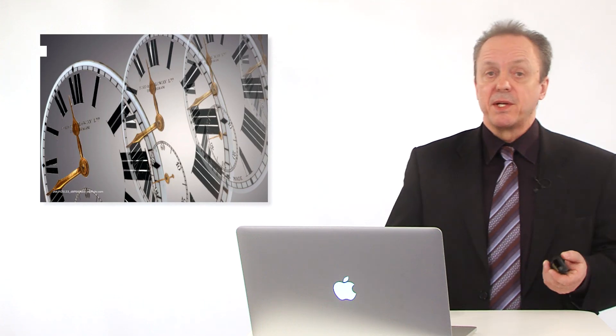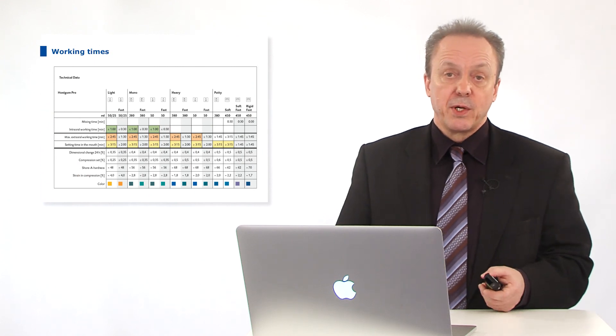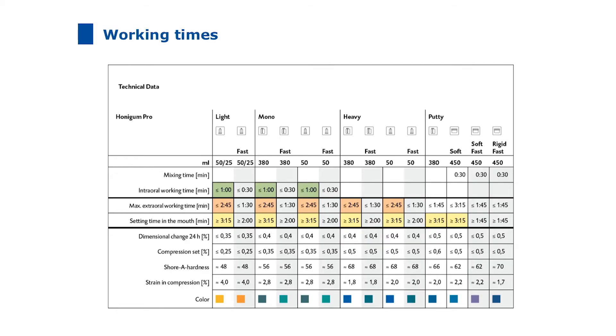You know the many different materials with many different setting and working times. Even if you want to go faster, Honigum Pro has the ideal impression material for you. For all Honigum Pro mixture materials, we now have the same intraoral setting time of 3 minutes and 15 seconds. And when it has to go faster, all variations are available in a fast version as well — the setting time in-mouth is only 2 minutes, and in our putty fast hand-mix version even only 1 minute 45 seconds. For complete recovery after deformation of the impression, please allow 30 minutes.